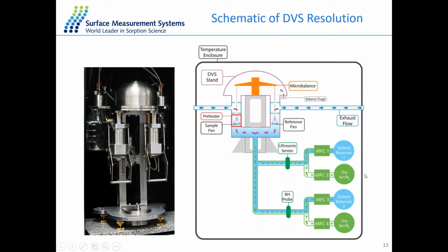The carrier gas for the system could be dry air or nitrogen. And there are two bottles at the back here. One is for water and one is for organic vapors. So the mass flow controller inside the system will control the flow of the carrier gas and the saturated vapor in ratio to get a certain level of humidity or partial pressure.